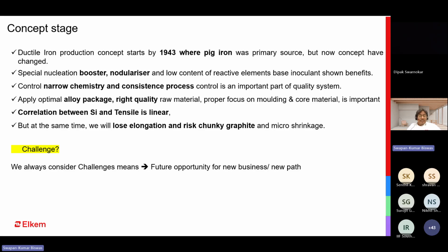Also, the trace content, in the case of ductile and gray iron: in most cases people focus on a few elements, 4-5 elements, but they overlook the trace elements, which are most important when you are going to produce good quality castings. When you go for stringent and most critical casting production, narrowing down the chemistry is also most important, along with a consistent process. Otherwise, it will be difficult to maintain quality heat by heat. And you have to decide which package combination is right, considering your product portfolio and the configuration of these castings.